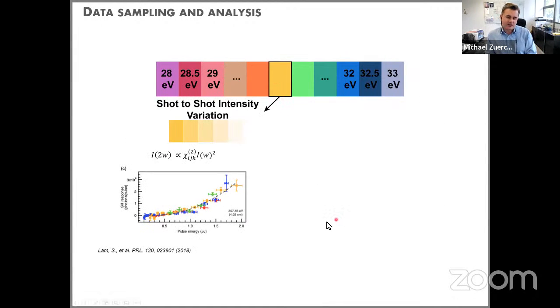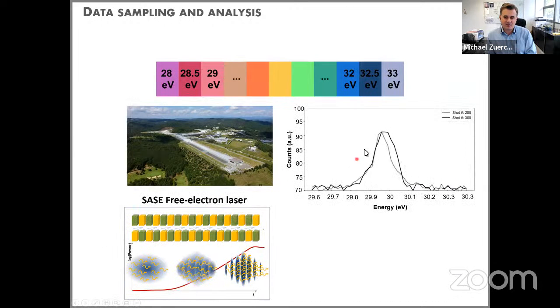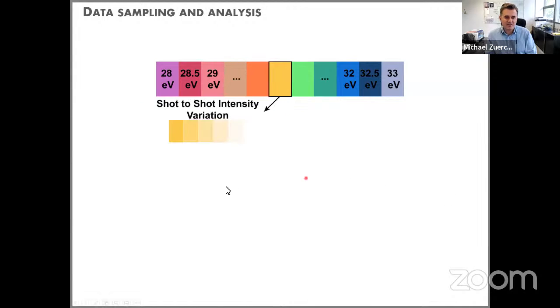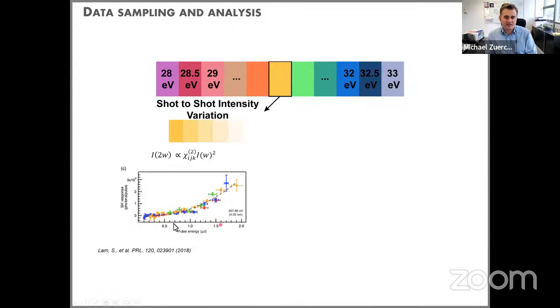Now, to do these experiments, what seems like a bug, and a lot of free electron laser users don't like these fluctuations, but have to work around them. In some experiments, they will just take the very clean shots for certain types of physics that people want to study. In this case, it's actually an advantage, because what we need for our measurements is anyway different pulse intensities or pulse energies at the input side of the experiment that impinge on the target. So essentially, the fluctuations we get in amplitude, automatically we can detect every single shot.